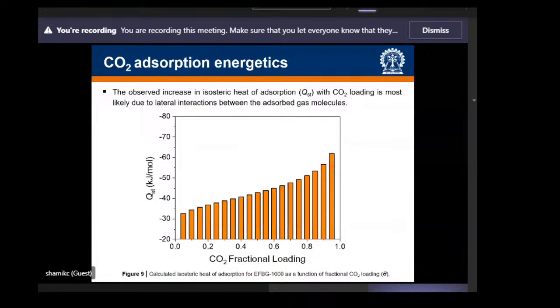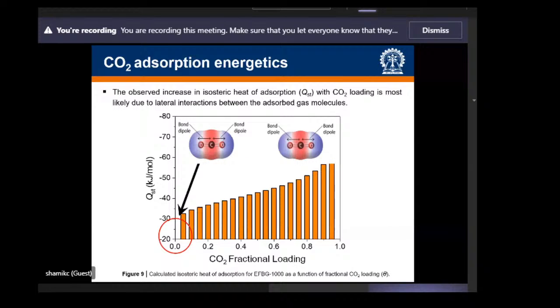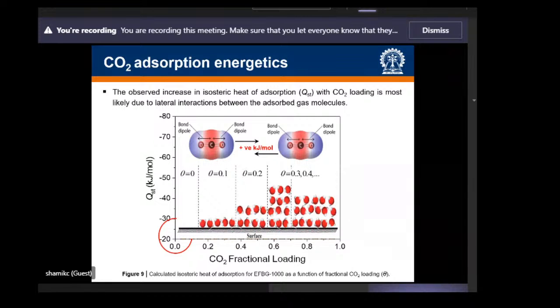Another interesting thing to note here is that we also measured the isosteric heat of adsorption, and we found that the isosteric heat of adsorption at zero loading was less than 35 kilojoule per mole. This isosteric heat of adsorption gradually increased with increase in CO2 fractional loading, suggesting that lateral interaction between the adsorbed CO2 molecules was mainly responsible for the adsorption process. So basically there was a positive interaction between the gas molecules, and it was more like initially a monolayer was formed, on top of which several other layers of gas molecules were formed. So with increase in surface coverage, the isosteric heat of adsorption gradually increased.